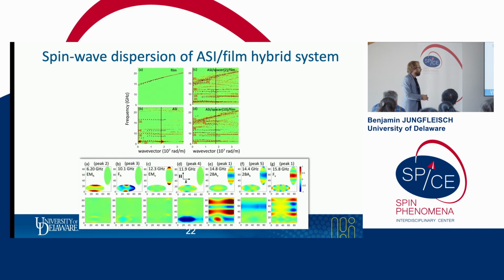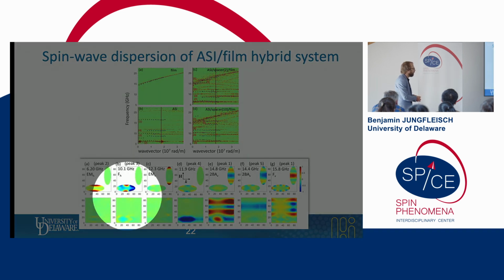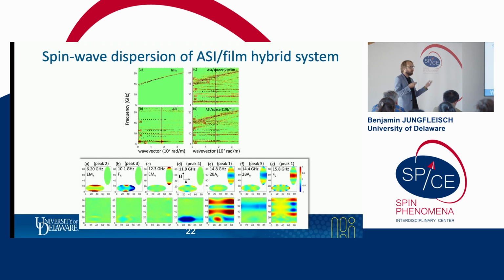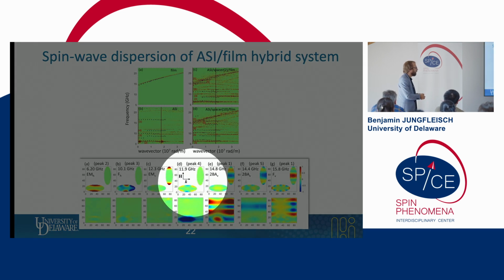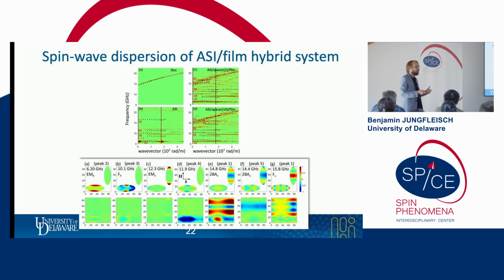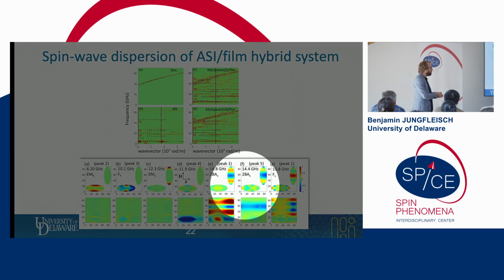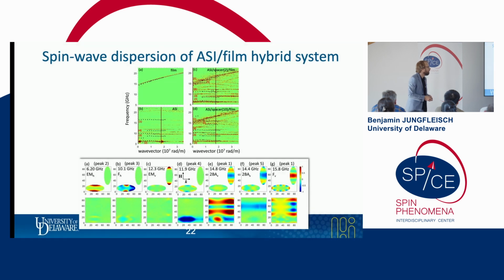So just to summarize this, if we are below the Damon-Eshbach frequency, labeled here in panels A, B, and C, the modes are uncoupled. You can have a static interaction, that's panel D, here peak number 4, where we have an effective field minimum, a well where the dynamics are localized. And we showed here this dynamic coupling, which is true for peak 1 and peak 5, panels E, F, and G, where we get a dynamic interaction that imprints the nodal structure of the artificial spin ice into the film underlayer.